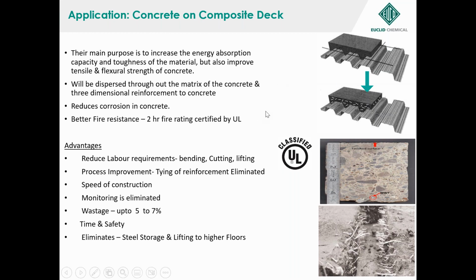Imagine you are talking about G plus 30, G plus 25, even a 1.5 day or 1.75 days saving per slab for calculation. If I take 2 days, you're talking about almost 45 to 50 or 60 days you save only by eliminating the steel in this process. Steel construction itself is fast, and on top of it, with these macro fibers, you are increasing the speed of construction by almost 1.5 to 1.75 days per slab.